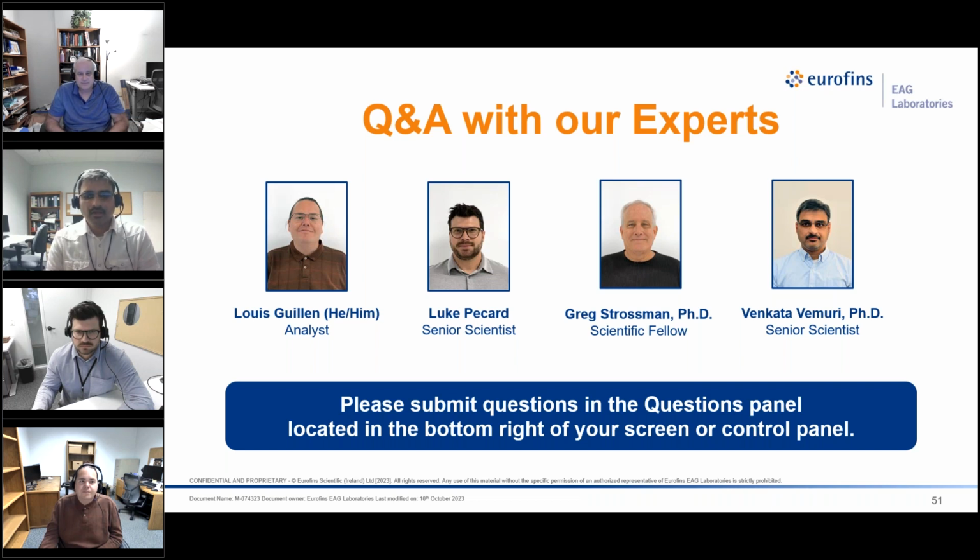Yeah, we can detect fluorine, chlorine, iodine, and the detection limits are dependent, as I said in the presentation, on the atomic number. So for fluorine, we have a decent detection limit of 2 to 3%, but for iodine and chlorine, we have much better detection limits. For example, for iodine, we have 0.03 atomic percent. For chlorine, we have 0.5 atomic percent detection limits.